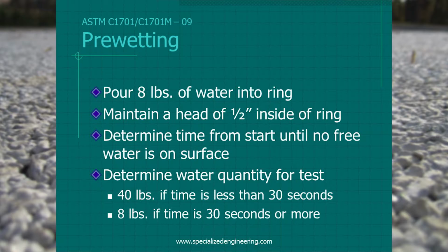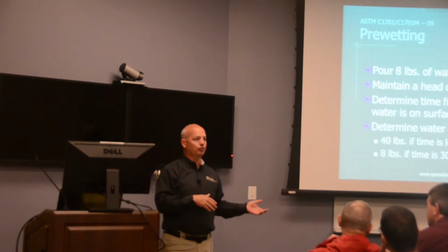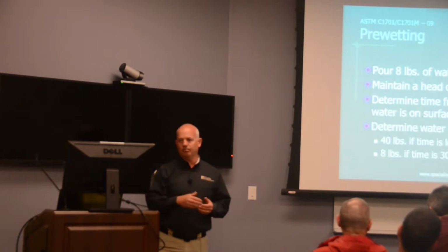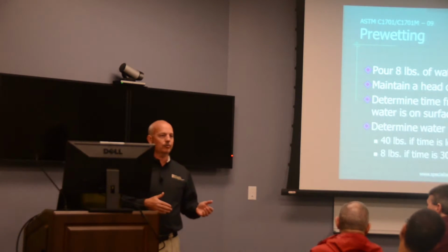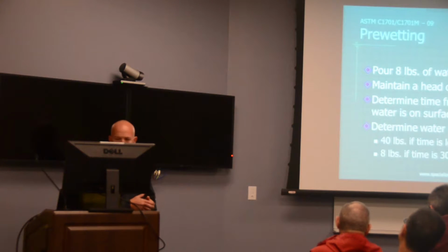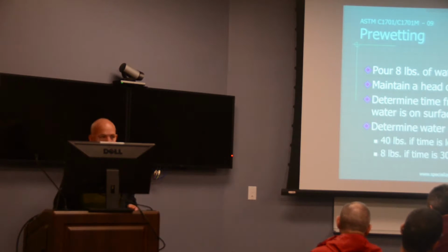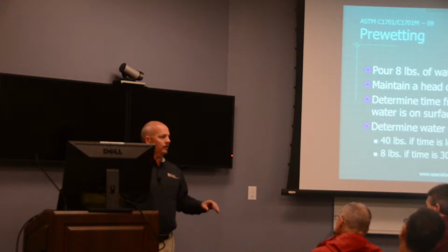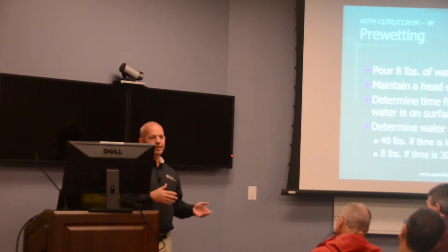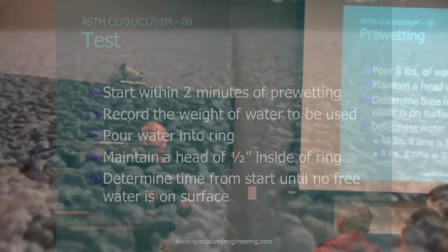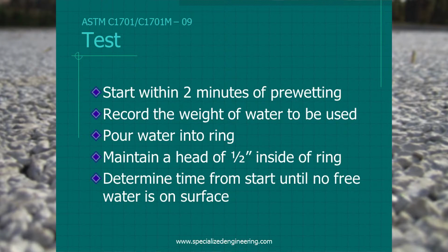And then you're timing it. So from the time that the water first hits the concrete until you can't see any water on the surface anymore, and you record that time. So that's called the pre-wetting, and that determines how much water you use for the actual test, based on the time it takes for that 8-pound pre-wetting to occur. So if that water goes through in less than 30 seconds, then we'll use 40 pounds for the test, 40 pounds of water. If it's more than 30 seconds, we'll use 8 pounds of water for the test.